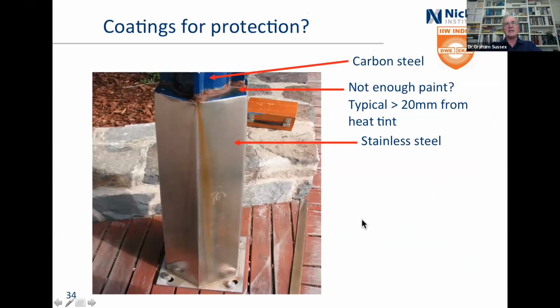Okay, so let's get serious about looking at welding and galvanic corrosion. Here we've got a lovely piece of stainless steel down the bottom, and here we've got a piece of painted carbon steel up the top. And we've got corrosion around there and draining down there, and that's not good. What happened? Well, the first thing that happened was that they didn't clean all of the muck off the weld, so that the paint just fell off.